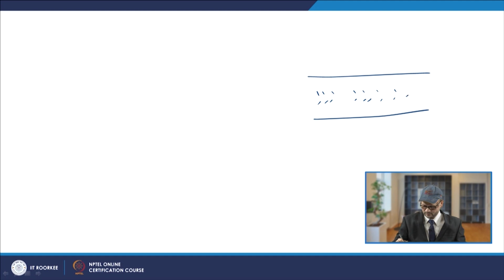So you will have these cracks normally in thick section carbon manganese plates, where you have high heat input processes like SAW. These type of cracks are caused because of the loss in ductility in the steel, so that we will discuss. So that is known as the chevron type of crack. This is your chevron cracks.